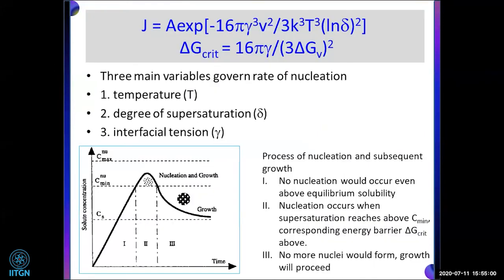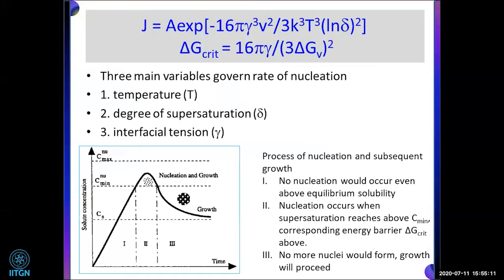And one more thing that is important: when we want to prepare this kind of nanoparticle, say surface active nanoparticles for catalysis, we have to tune the synthesis of the nanoparticle very effectively. This equation is the classical theory of nucleation, where J is the nucleation rate. In this equation there are three variables: one is the temperature, one is the degree of supersaturation, and the other is the interfacial tension.